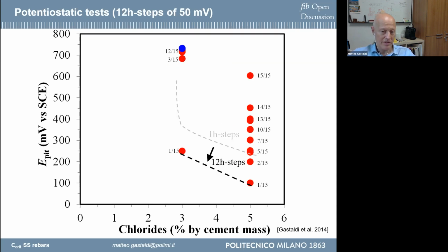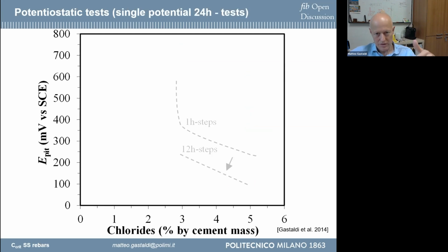If you change the parameter of the test, for example, you make a step of 12 hours, you can observe that you obtain another diagram that gives you an initiation of corrosion at a potential that is lower. This is normal because 1 hour is probably too fast. It's a test that is too rapid. If you make a test that is not so rapid, you can obtain a pitting potential that is lower, that is closer to the real condition. Then when you move from this condition, in which you have a change in time of the potential, to a test in which you fix the potential, you can obtain something that is probably closer to what is present in the real condition.